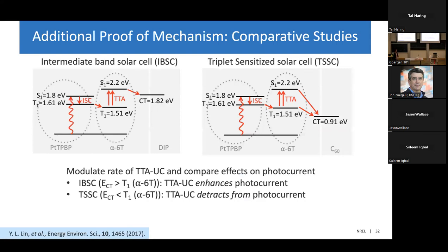As an additional proof of the mechanism, we also performed some comparative studies with a related but slightly different solar cell called the triplet sensitized solar cell. So in this device, we're replacing DIP as our acceptor with C60. And instead of getting a donor-acceptor charge transfer state that is higher in energy than the triplet of alpha-6T, we now have a charge transfer state energy that is lower and can collect both singlets and triplets from the alpha-6T. And the reason why this is an interesting comparison is because now if we were to modulate the rate of triplet-triplet annihilation in both of these devices, we expect it to have different effects on the photocurrent. So for the intermediate band solar cell, because only charge dissociation can occur from the singlet level, the more TTA we have, the more singlets we produce, and that's going to give us more photocurrent. So it should enhance the photocurrent.